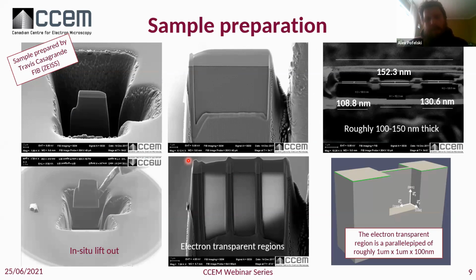The other thing that is important to keep in mind is the sample preparation. That has a significant impact on the strain results. So here I'm just showing a classic flow of a sample preparation using FIB. This will be an in-situ lift-out here. For more details, I actually recommend going to Travis' presentation, the webinar for the CCEM, that will explain the whole process in detail. I'm just going to go through the key elements that will have an impact regarding the strain. So when we have to make an electron transparent thin foil, that's the importance of the sample preparation method.